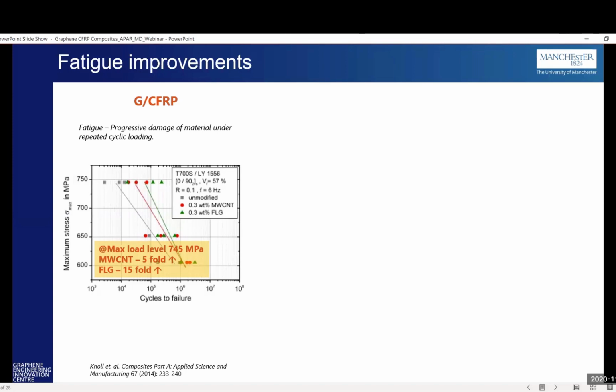So anything that can be done to delay the progression of this crack increases the durability of the material. That's where graphene can actually help. In this particular study, by adding just 0.3% of few-layer graphene to the resin, they were able to increase the fatigue life of the material by nearly 15 times. When you compare it with multi-walled carbon nanotubes, they were only able to do it for 5 times.